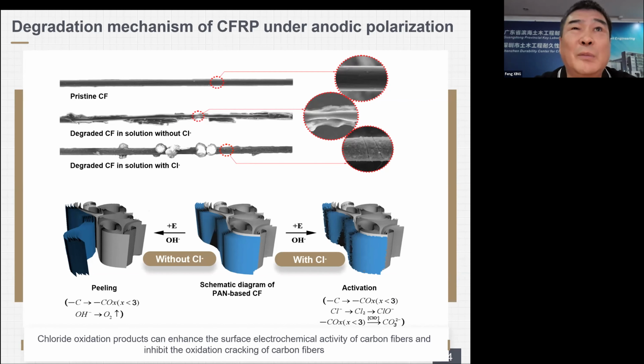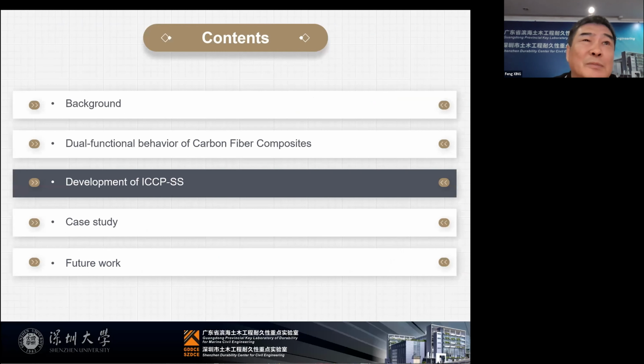As can be seen from SEM, chloride ions can inhibit the oxidation cracking of carbon fiber under polarization, maintain the good microstructure of carbon fiber, and thus improve the tensile strength of CFRP after polarization. From the material aspect, this is why carbon fiber material can be used as both anode and strengthening material, and especially suitable for the coastal environment dominated by chlorine ion erosion.